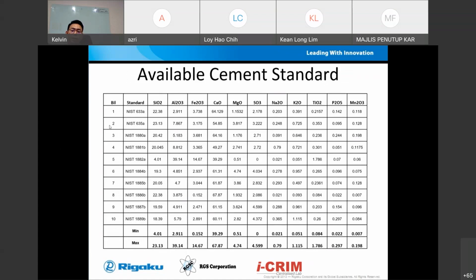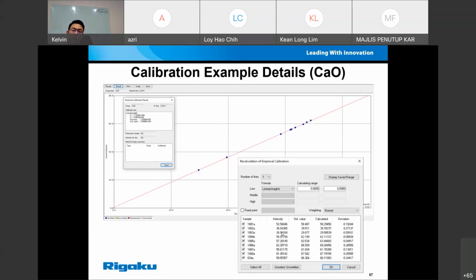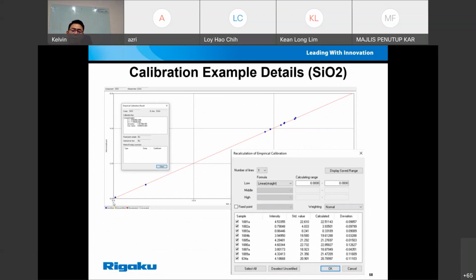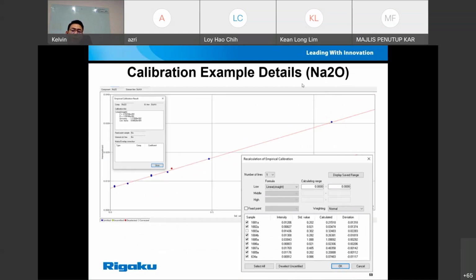This is the NIST standard available. Mostly it is all cement standards, which can cover this kind of range. And this is an example calibration curve, a fusion bead curve. As you can see, it is very linear and the correlation is very good, about 0.99 something. These are a few examples: silica oxide, and even sodium, which has a very low concentration and a very low intensity, can also get a very good correlation.